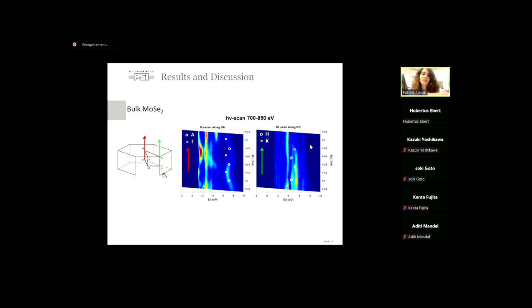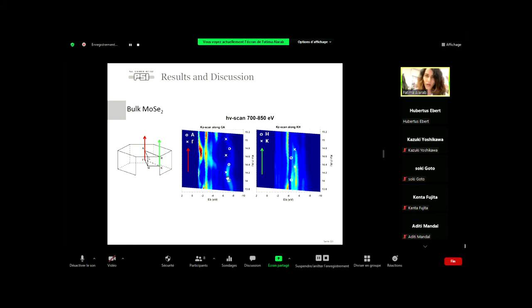And because actually the C vector here is very small, the difference in photon energy between K and H is really very, very narrow. So one has to really be careful about how to find the points. So that's why we did a KZ scan. I took a cut along the gamma A direction and another cut along the KH direction. And then by following the periodicity, we can find the points that correspond to gamma A or KH and so on.